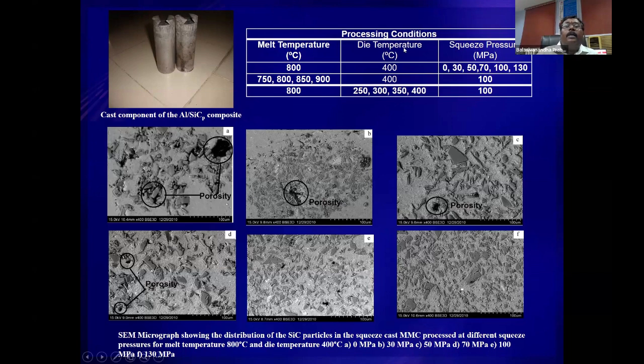So these are all the process parameters that we have studied: varying the melt temperature from 700 and 750 to 900, and keeping the die temperature in different situations, 250 to 400 degrees centigrade. And also by changing the pressure from 30 MPa to 130 MPa, we have seen how the microstructure is changing. Zero squeeze pressure is like conventional casting, and that clearly indicates a lot of agglomeration. Even though you assume that in the melt you have created good conditions with a homogeneous distribution, after solidification you could see a lot of agglomeration.